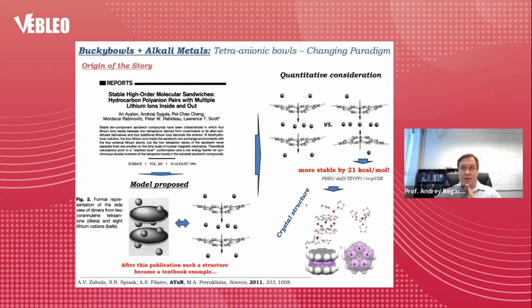What is also important about this system is if you look at it from the potential batteries point of view. We can recall that graphite-based materials, like the lithium batteries we use nowadays in almost every electronic device, have a theoretical limit. This limit, a lithium per carbon ratio equal to 1/6, is fundamental, and you cannot overcome it. So you need to modify your system chemically.